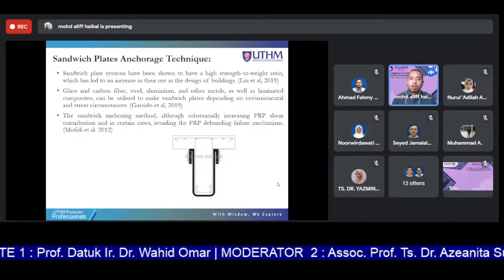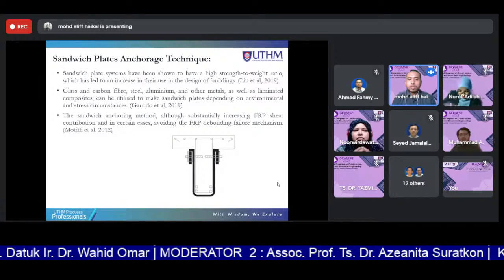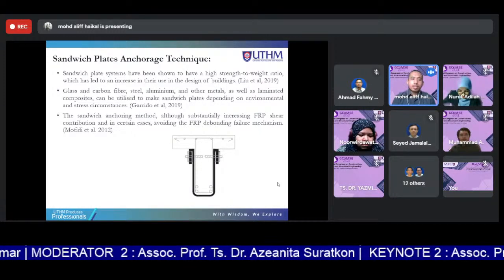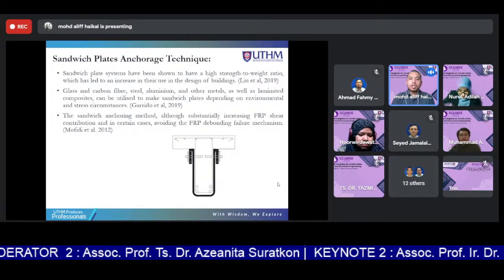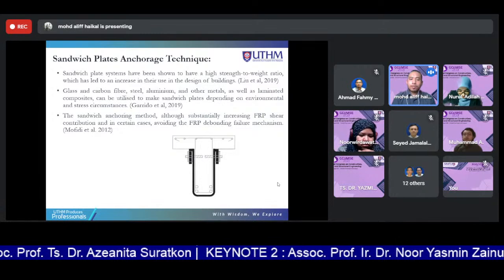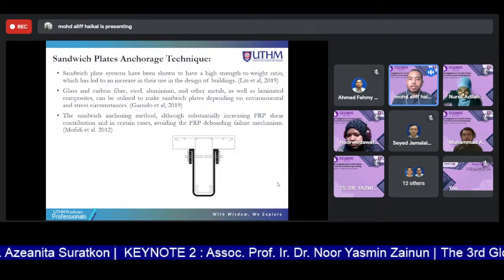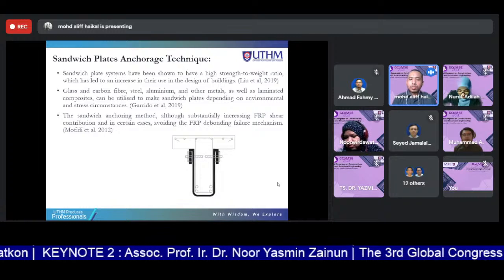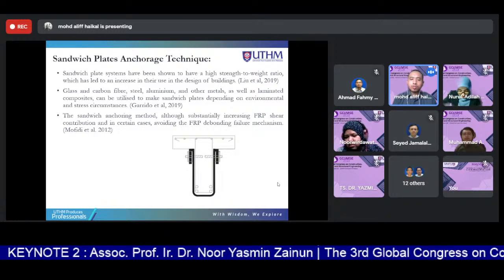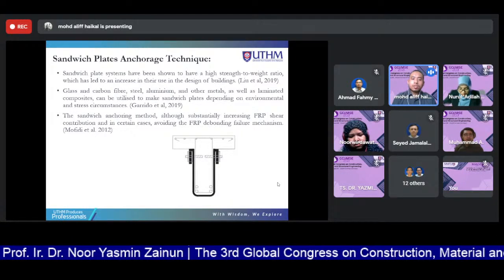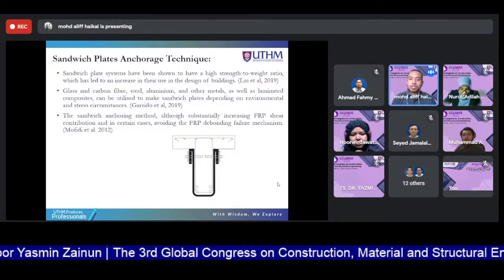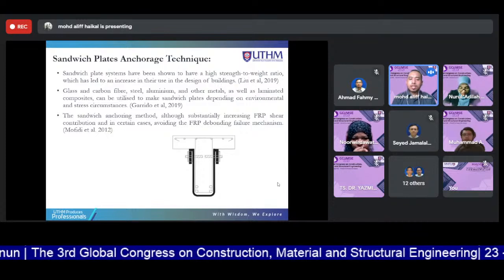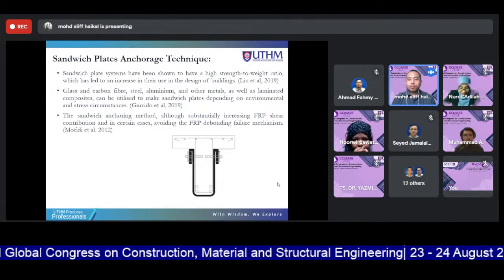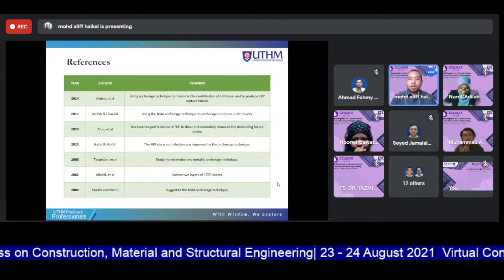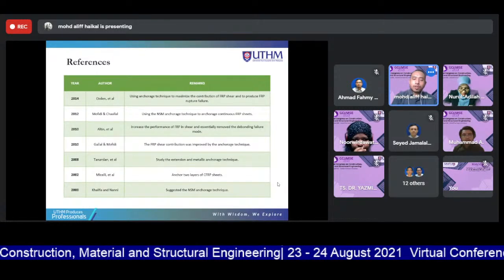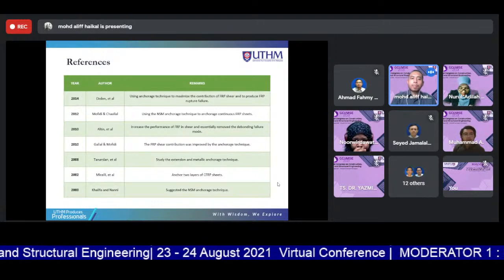For the sandwich plate anchoring technique, sandwich plate systems have been shown to have a high strength to weight ratio, which has led to an increase in their use in the design of beams. Glass and carbon fiber, steel, aluminum, and other metals, as well as laminate composites, can be utilized to make sandwich plates depending on environmental and stress circumstances. The sandwich anchorage method also substantially increased FRP shear contribution and, in certain cases, avoided the FRP debonding failure mechanism. This is a reference that I use for the research.